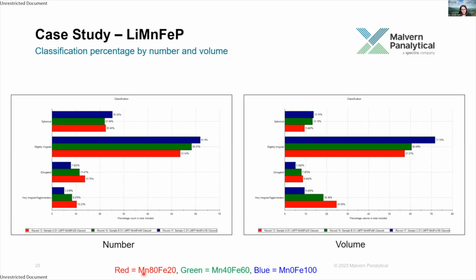And then because we've done this for each of the materials, we can then compare the percentage of particles that fall into each class. So here we've shown the number-based classification chart on the left and the volume-based classification chart on the right. And comparing these three materials shows that with increasing manganese content, so going from the blue to the green to the red line, we're seeing more elongated and irregular shaped particles in the material.